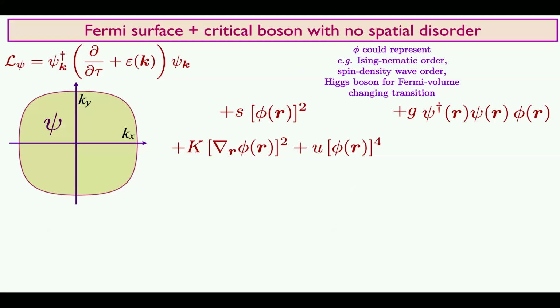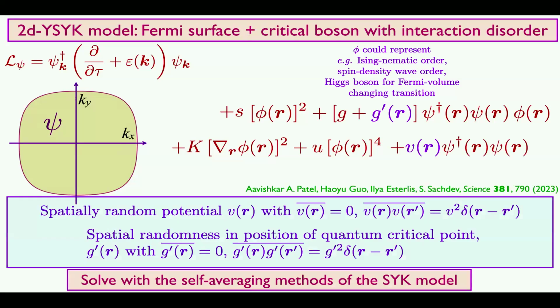Here's a little more detail for the theory. You have the Fermi surface psi, you have this mass for the boson, and then the Yukawa coupling. Well, the missing ingredient is impurities. So let's add some impurities. The way you normally add impurities in the theory of metals is as a potential for the fermions, which you have to do here too. In the usual Boltzmann theory, you have elastic scattering that comes from here, and then inelastic scattering from electron-phonon or electron-electron interactions, and then you use Matthiessen's rules to just add them up. Here, you can't do that.